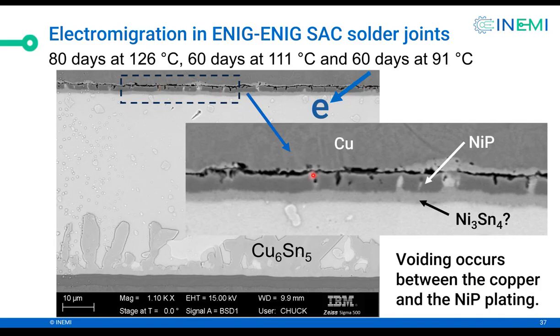So okay, here's copper, here's nickel phosphorus, and then Ni3Sn4, the very thin layer. But you see cracks in the nickel phosphorus. So I think that's where the copper atoms diffused through. So here is the magnified view. So you can clearly see the voids, and you can see porosity in the nickel phosphorus plating. And this is the Ni3Sn4.